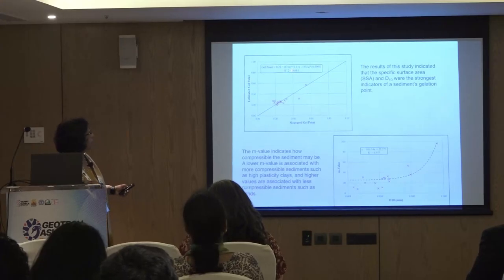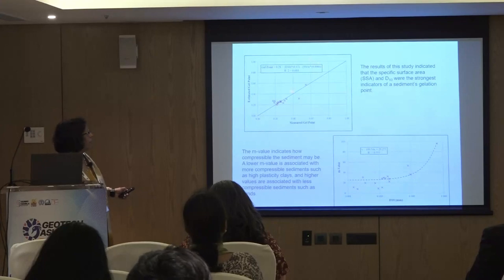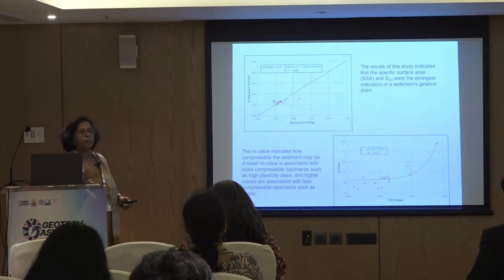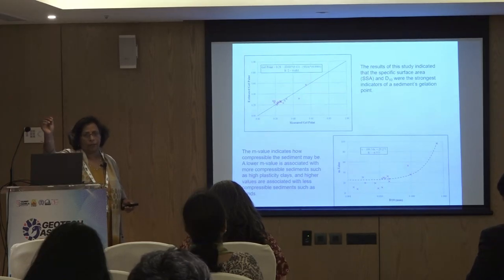Well, if we know the D10, which is grain size distribution, and specific surface area, these are simple tests to perform, and using these values we can estimate the gel point or percentage solid in the field without doing a large scale test.